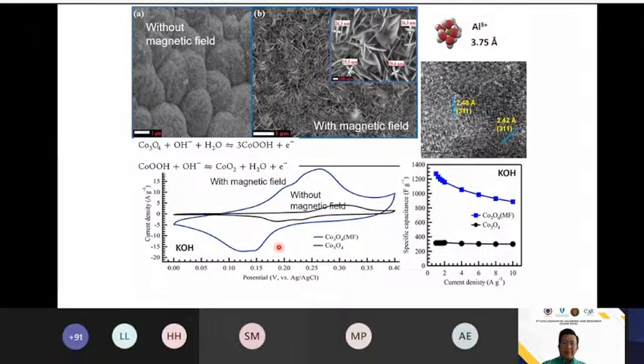But we ran it on this aluminum ion, and it is proven that it couldn't work, because the aluminum ion is too big to get trapped inside this cobalt oxide structure. We can only get this high performance in the potassium hydroxide. So we did not succeed, because we want to devise a metal oxide that can trap the aluminum ion.